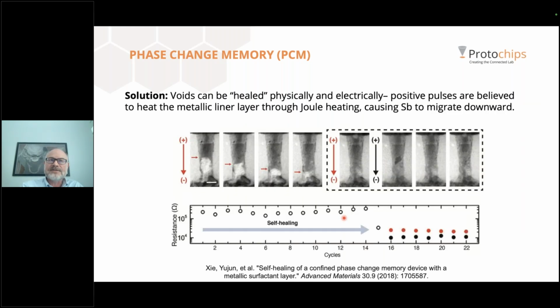And they discovered a solution using in situ techniques. What they found is that you could heal it by forcing current through the cell. This heated up that metal liner around it. And after several positive pulses, the heat that was produced forces the antimony back down towards the bottom, and the cell begins working normally.